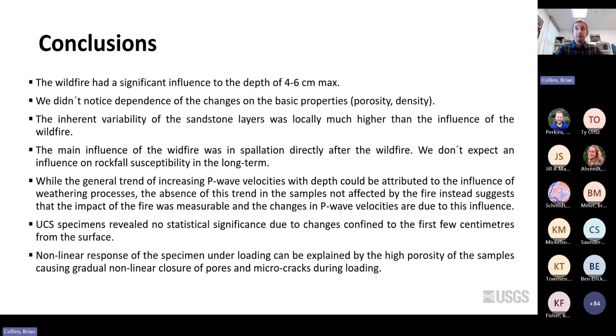And this variability was already there before the wildfire. And actually the wildfire caused some sort of unification of the surfaces that were exposed to it. Also, there was a big variability within the fire itself, because in places where there was a tree that fell down and was touching directly the rock face, we observed much more spalling than in other areas, obviously.